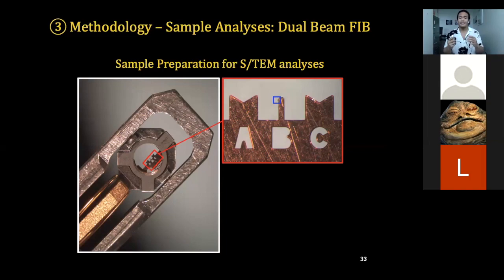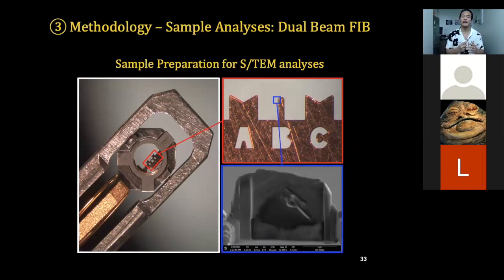In the middle of that second image is a blue box where the actual sample is. As you can see, it's very tiny. And a zoomed in image of that is the actual sample that we analyzed for this project. You can see that it's been thinned out to the appropriate thickness required for our next instrument, which is approximately 100 to 150 nanometers.